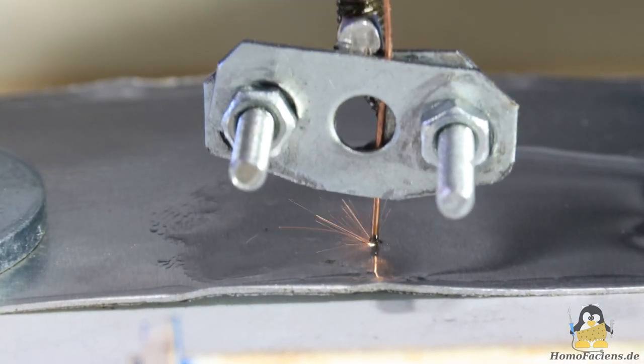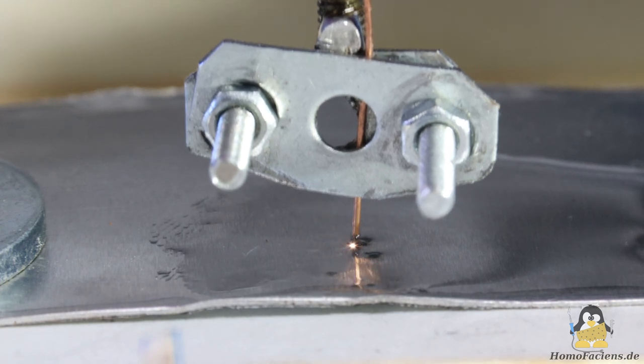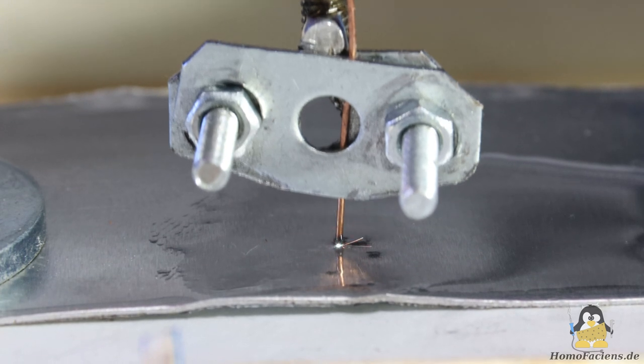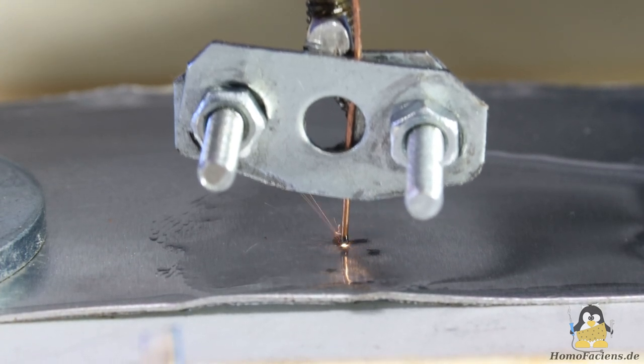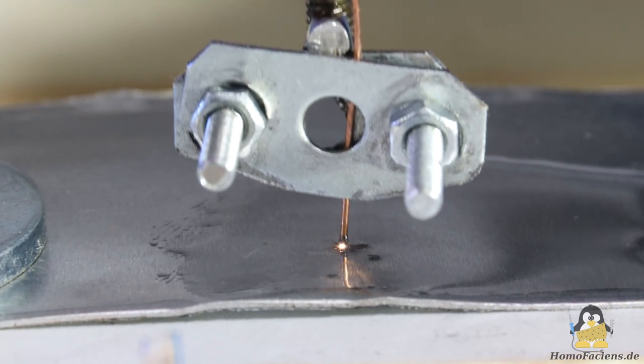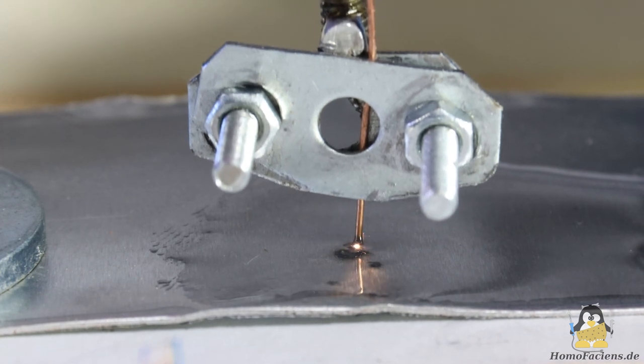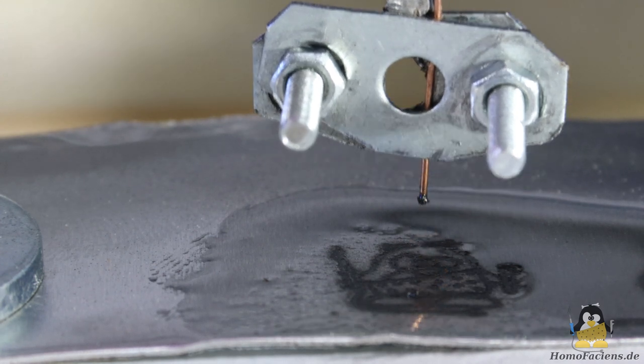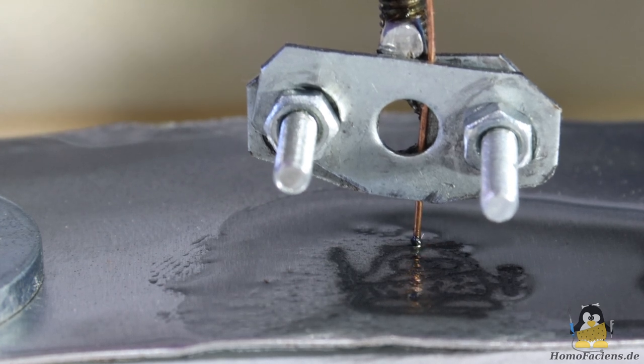The softest metal with the lowest melting point in my series of experiments is the trickiest. It finally worked with the 0.7mm copper wire and sunflower oil on the workpiece. I also reduced the feed rate to 0.5mm per second.